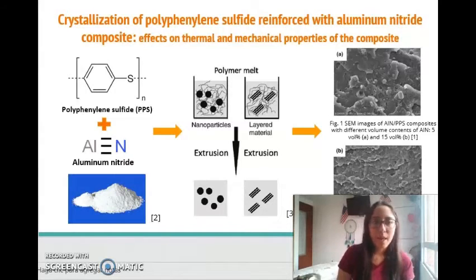damage tolerance. So in this article, they included aluminum nitride, a mechanically hard material with a high melting point and excellent thermal conductivity, to get aluminum nitride and polyphenylene sulfide composites. They were prepared by a melt blending method. In this method, inorganic nanoparticles are dispersed into the polymer matrix, and the polymer nanocomposites are obtained by extrusion, like this.